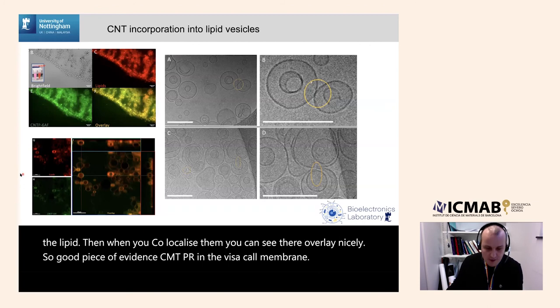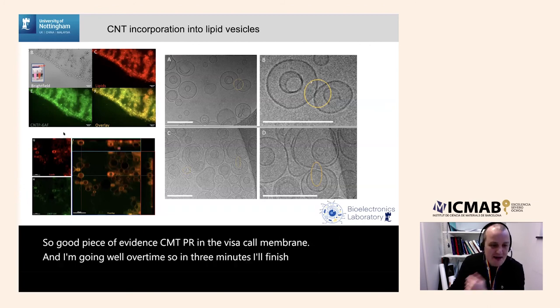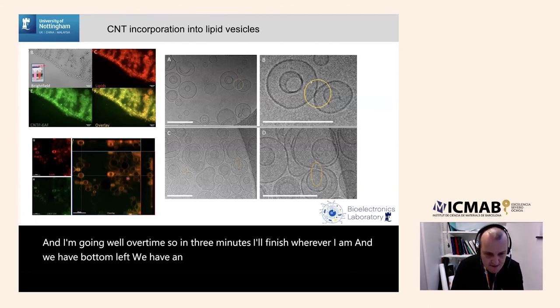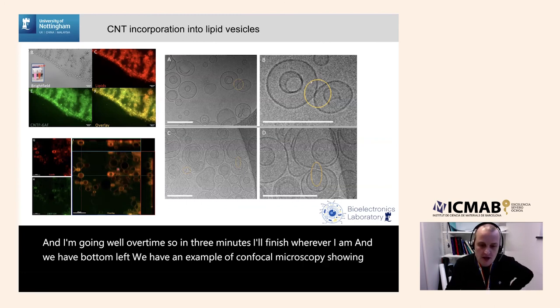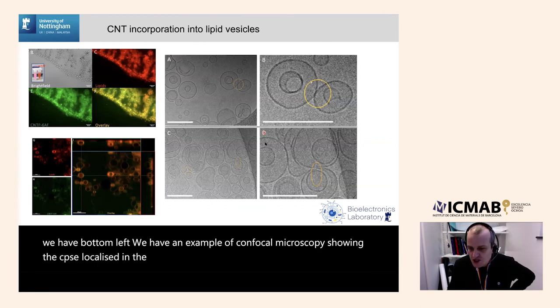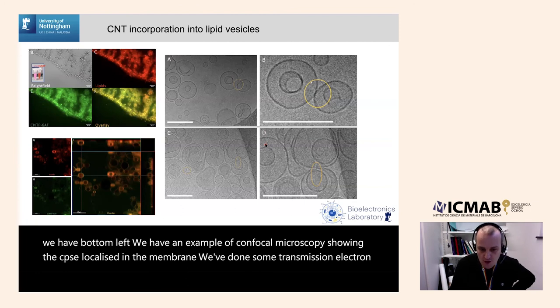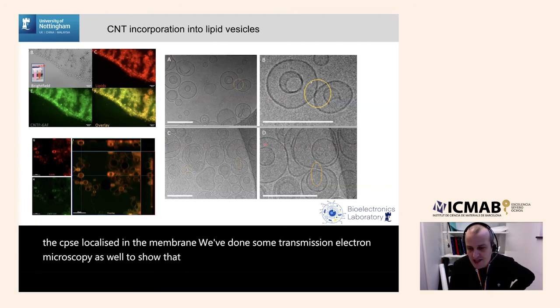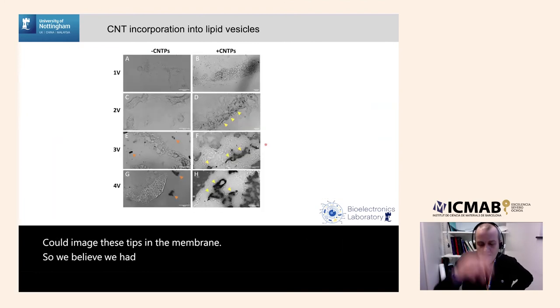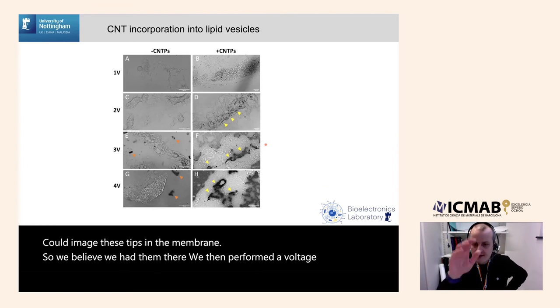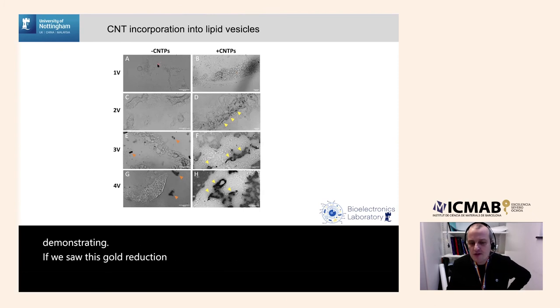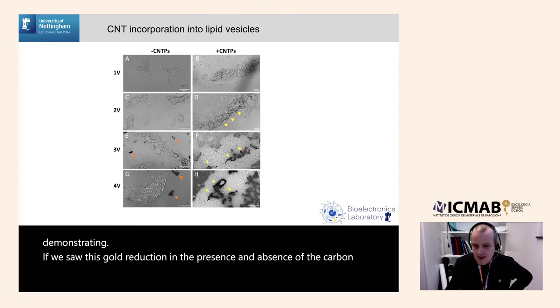And I'm going well over time, so in 3 minutes, I'll finish wherever I am. We have an example of confocal microscopy showing the CNTPs localized in the membrane. We've done some transmission electron microscopy as well to show that we could image these CNTPs in the membrane. So we believe we had them there. We then performed a voltage study demonstrating if we saw this gold reduction in the presence and absence of the carbon nanotube porins with the vesicles.